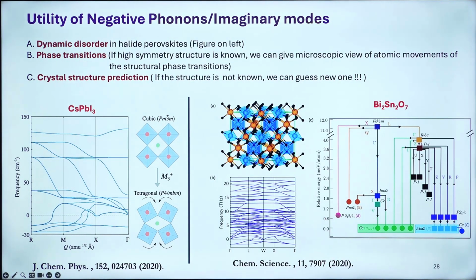CsPbI3. Then phase transformation: if the high symmetry structure is known, we can give a microscopic view of the atomic movements of the structural transformation. Then crystal structure prediction we can also do. If the phonon modes are negative, then one can try to see how we can evolve to a new structure by freezing that mode.